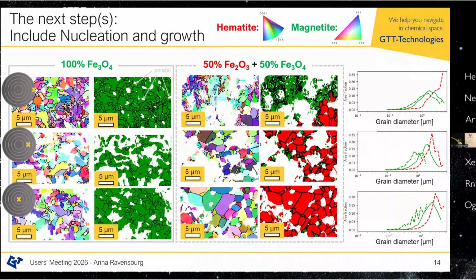And then if we go towards the surface, we have more of these green grains, and at the surface, we're already more reduced. We can look at how these grow, we can look at where these grow, and we can try to take this into account. For example, by plotting this, that you see on the right side, and this is now included in our model, so that we have the grain size distribution. The left side, the 100% conversion, is these curves, the ones that are not dashed, and we have the dashed ones, which are the in-between ones. You can see that the green one, for example, first nucleates here and has smaller grains, and then the grains grow, so it moves to the right.